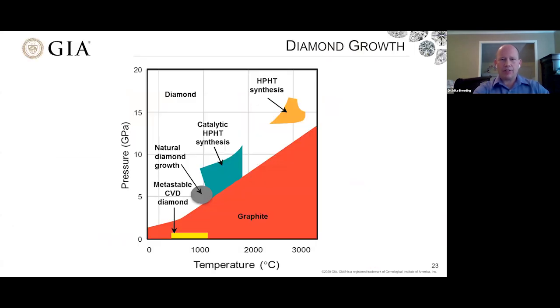Before you say I do to anything, you really should understand it a little. Here's a phase diagram — a measure of pressure on the vertical axis increasing upward, with temperatures on the horizontal axis increasing to the right. In this gray oval is where most natural diamond grows — about five to six gigapascals in pressure and roughly around a thousand degrees C. The white area is where diamond is stable or would grow if you have pure carbon, and the red area is for graphite. Diamond and graphite are both pure carbon — they just have different atomic structures, which gives rise to their very different properties.